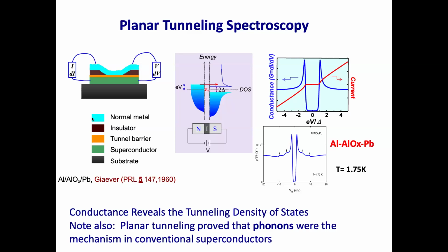One of the cool things about BTK was I was always trying to measure just the background. And when I was a kid, we didn't understand the proximity effect. And now we kind of understand it as all Andreev reflection. And so what happens if you have two materials that have a very different mass intrinsically, so you have a very different Fermi momentum, that decreases the chance of tunneling. It decreases the chance of Andreev reflection. You have an electron going from a low Fermi momentum material to a high Fermi momentum material, and it doesn't Andreev reflect. It bounces back.